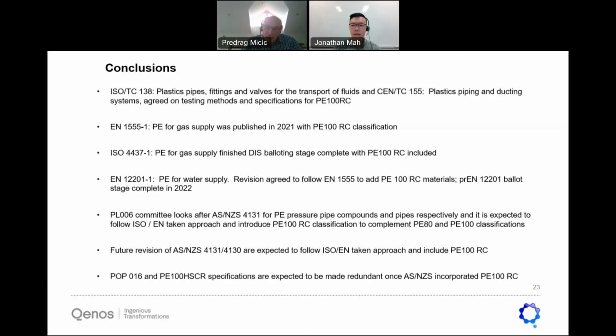It's an excellent question and a very practical question, and this won't change to normal PE100. A lot of temperature durability at the higher temperatures, the molecules give you that, but also additives give you that. So a lot of resistance to higher temperatures comes from the additivation, and it's very specific know-how there. How you make sure that all these molecules that give you all this strength do not change due to degradation at exposure to high temperatures over a long time, which was one of the problems with the test at 80 degrees for 1 year. After 1 year, the polymer starts to degrade at 80 degrees.